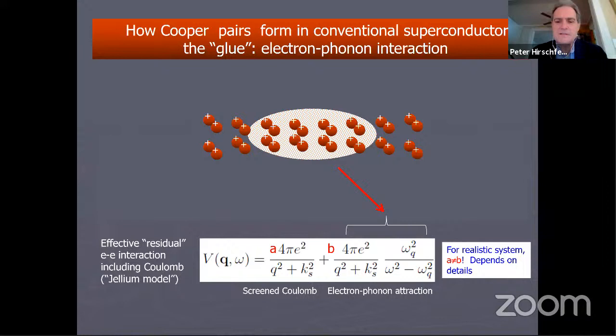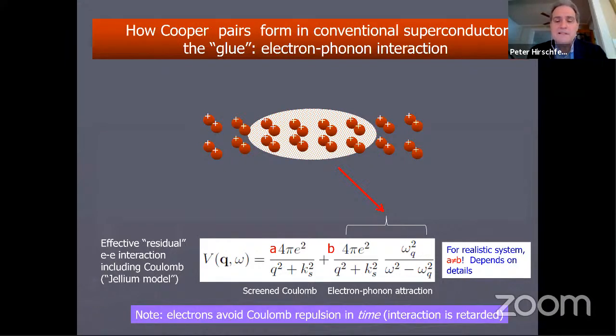But what happens is, if you do a more exact calculation, these two terms are still present, but they acquire essentially different prefactors. So that means that one term can dominate or the other term can dominate, which means you get a superconductor or you don't get a superconductor. Before I leave this slide, I want to just note that the essential physics here was that the electrons could avoid each other in time. They weren't in the same place at the same time, and therefore there isn't a static Coulomb interaction that affects them. And that's important. The electron-phonon interaction is frequency dependent.